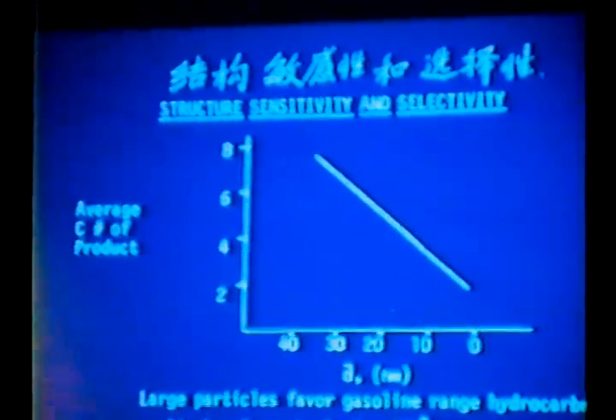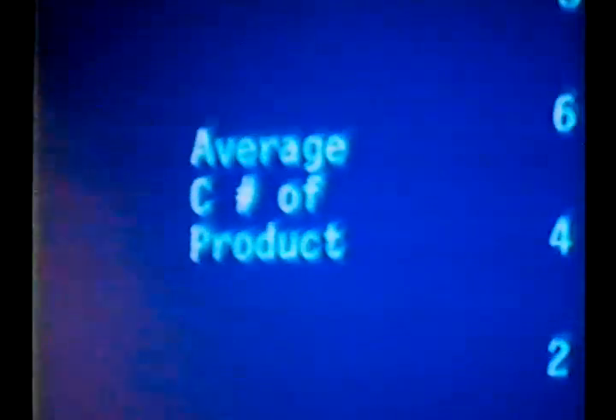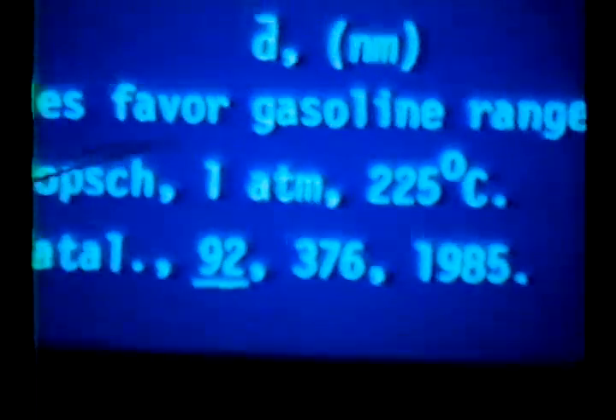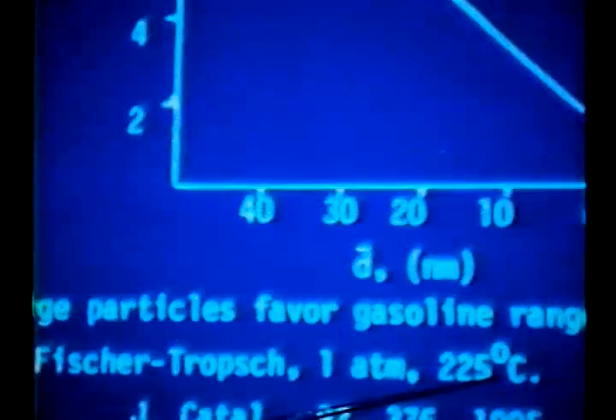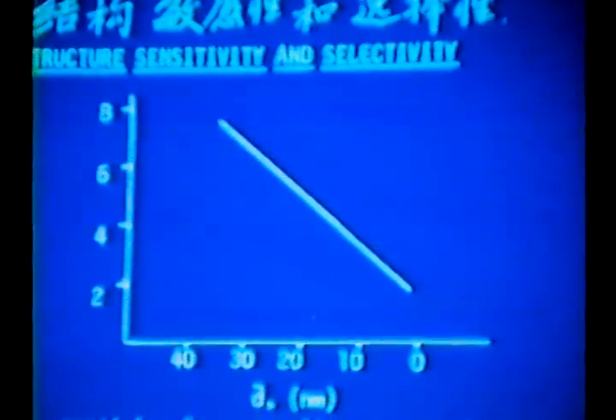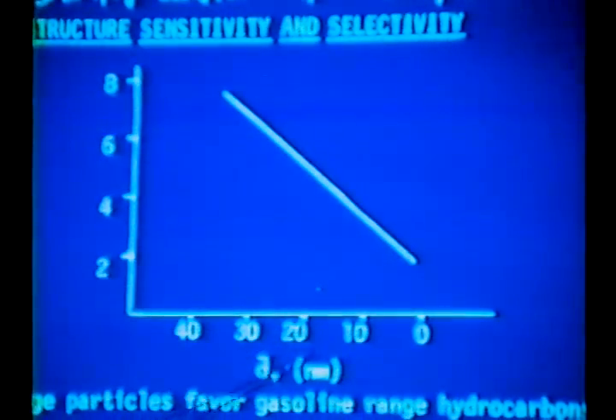This is some work from Cal Bartholomew's lab in Utah. What he's basically found is that in the Fischer-Tropsch reaction at 1 atmosphere and 225 degrees centigrade, the average carbon number of the product does go down as a function of particle size. Other people have verified this sort of thing as well. It's published in Journal of Catalysis in 1985. So there seems to be a structure sensitivity here in terms of particle size and Fischer-Tropsch activity for gasoline range hydrocarbons.